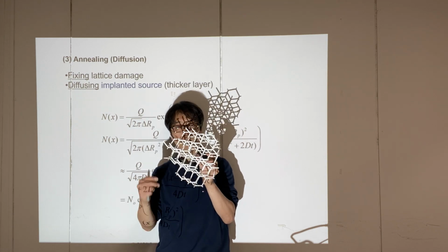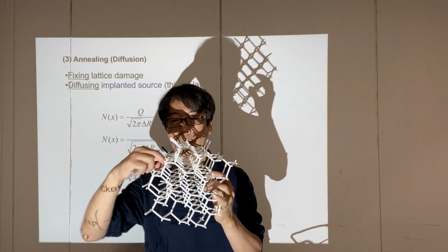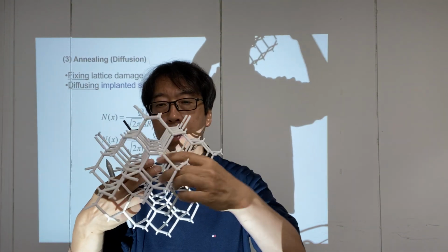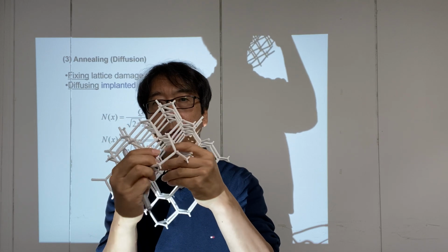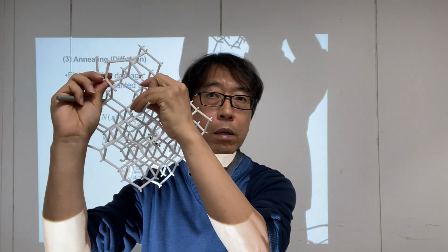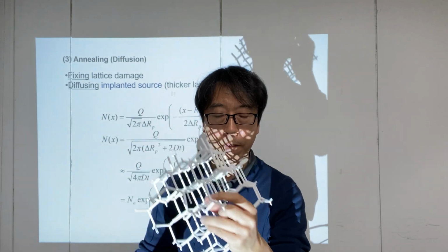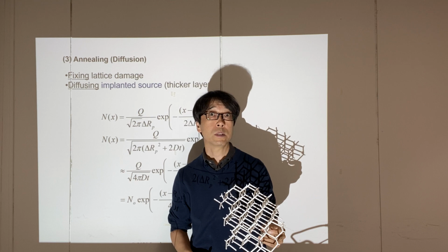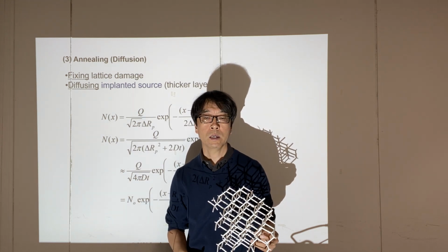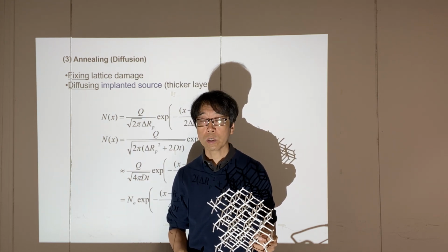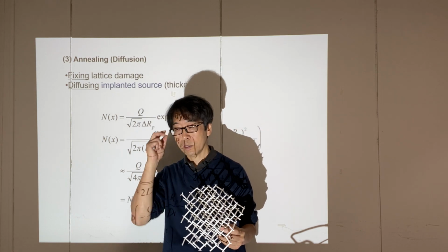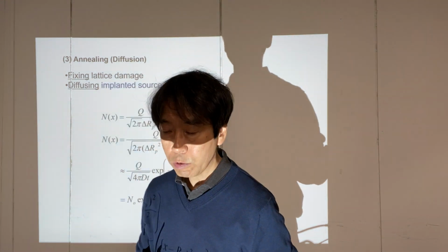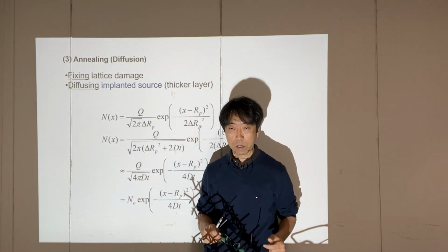When these atoms hit the lattice, what will happen? They will break apart. Look, they'll break like this. The lattice will break, and your crystal silicon will not be a single crystal anymore, and we lose all the good characteristics of this single crystal silicon. That's not really good. So how can you solve this problem? How can you fix it?